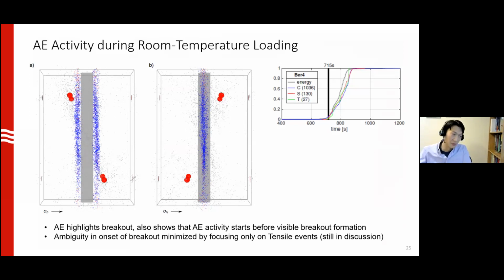We had quite a bit of discussion on how to use the acoustic emission to identify the onset of breakout. The acoustic emissions locate fairly nicely. So this is as we expected. It forms where the breakout should happen. I won't get into too much detail today, but essentially what we noticed is that we can classify the acoustic emission into source types: C for compressive, S for shear, T for tensile events. And it's really the onset of the tensile events, signifying the splitting open of the rock fragments, that corresponds with the onset of breakout. I can talk about this more in detail if interested, but in essence, that is what we rely on right now to identify onset of breakout.